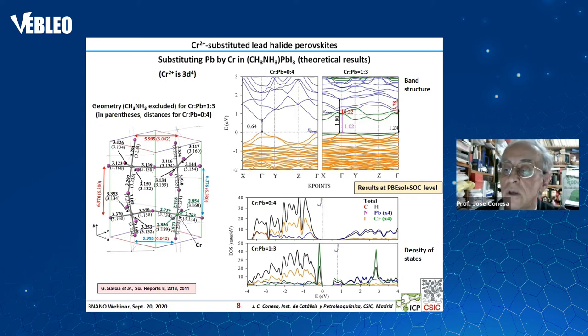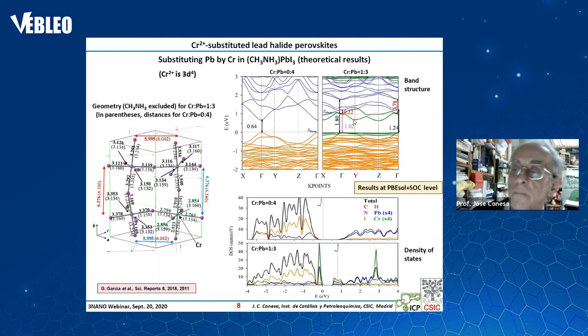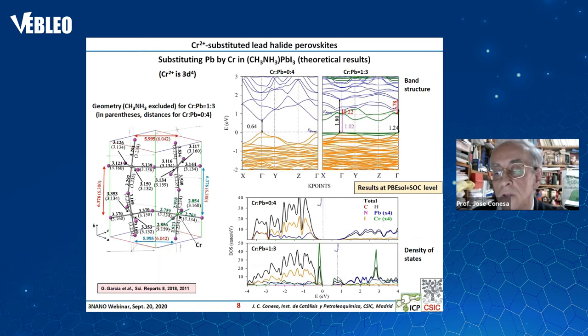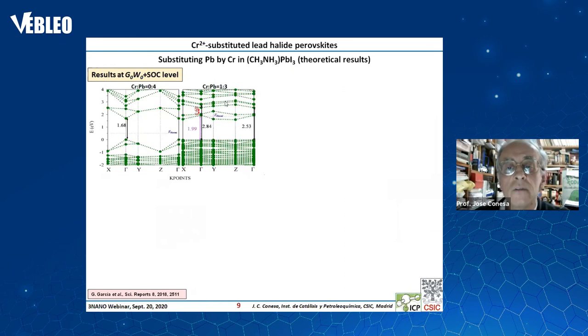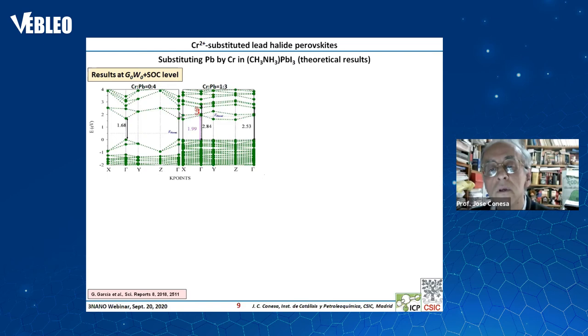We have been studying this with pure DFT calculations — but always with spin-orbit coupling included, because otherwise one would not be able to see any good effect. The DFT calculations show how we can have an ingap band in the case of chromium substitution: a new band induced by chromium appears. Then we have done computation at the GW level, again with spin-orbit coupling, and as you can see we now have an ingap band crossed by the Fermi level and well separated from the conduction and valence bands.